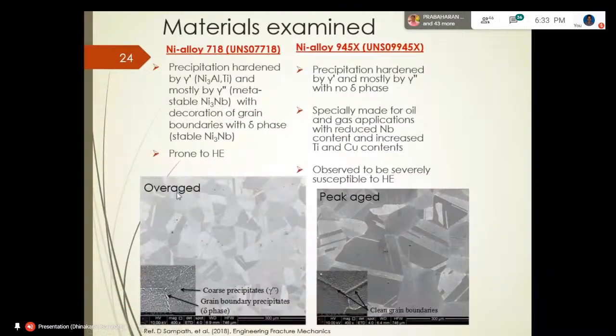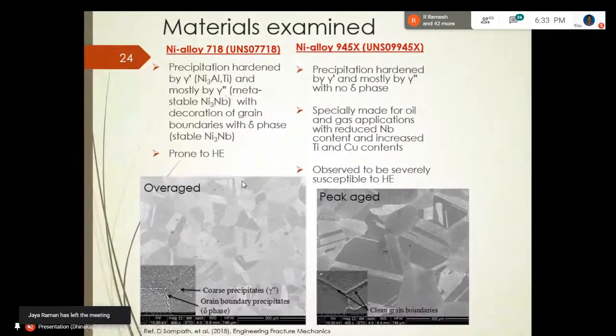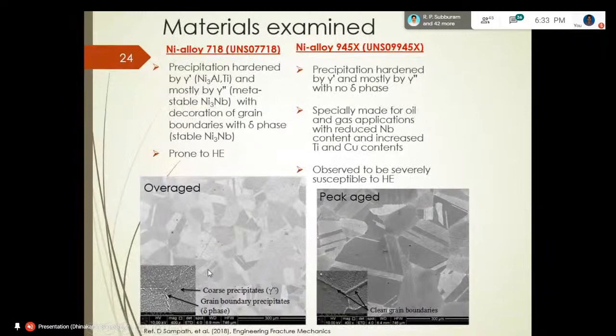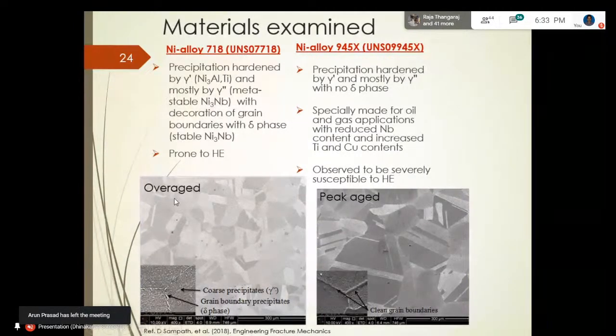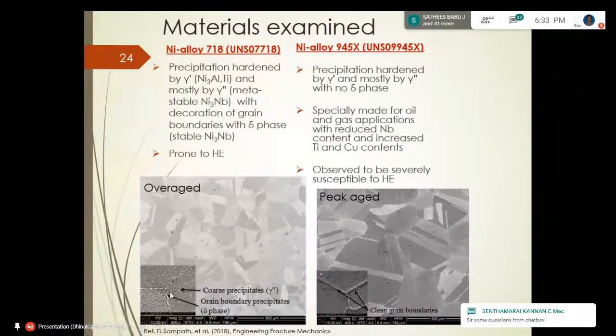So here, the overaged. So here, 718 has got gamma prime and gamma double prime precipitates. The major strengthening is coming from gamma double prime. They are of the size of hundreds of nanometers, sometimes even less. If it is in overaged condition, we saw something around 80 nanometers gamma double prime on the average, and also this has got delta phase at the grain boundary.